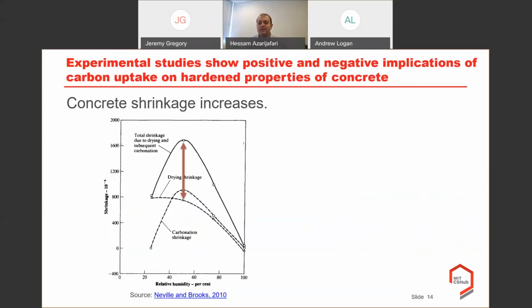The third and last one that I would like to talk about is the concrete shrinkage. The concrete shrinkage will increase as a result of the carbonation. When the hardened concrete is exposed to carbonation air, the weight of concrete will increase, and there is an irreversible carbonation shrinkage. And we can see that the carbonation increases the shrinkage at intermediate relative humidity, again, like we observed in the results earlier, that maximum carbonation will occur at intermediate relative humidity, and maximum carbonation depth also happens at the same rate. So just briefly mentioning why it has happened.